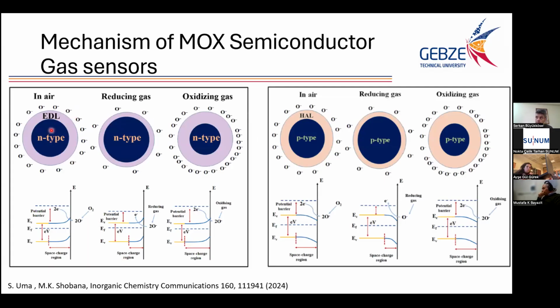So here what you see is an N-type material, a semiconducting metal oxide, and this semiconducting metal oxide absorbs some oxygen molecules which trap the electrons as oxygen ions on the material surface. Thus, an electron depletion layer is formed on the N-type material, whereas a hole accumulation layer is formed on the P-type material. These electron depletion and hole accumulation layers are called the space charge region. On the exposure of reducing gases, these trapped electrons are released back to the surface, and this changes the conductivity of the surface. So, releasing back the electrons increases the conductivity or changes the resistivity, and you can read this as a sensor signal.